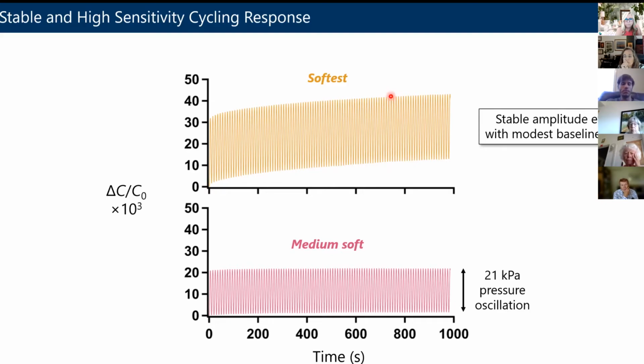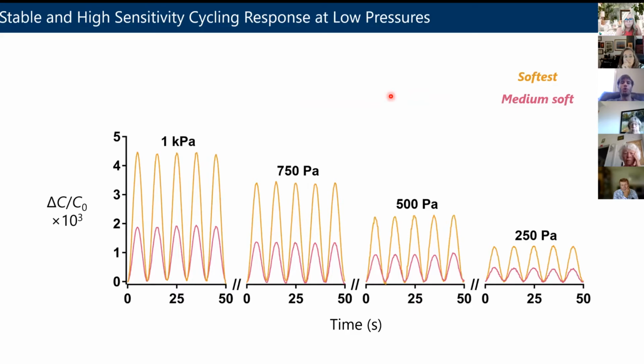You can actually go to even lower pressures than that 1 kilopascal we said was very low. So here's 1 kilopascal with those 2 different samples, the kind of medium soft and softest. And you can go down to even lower and lower pressures. And to orient you with what this magnitude is, 250 pascals of pressure is pretty close to if you've got your device sitting on the table and a fly comes over and lands on it. Now, that's not a lot of pressure, but we can pick that up using this device.